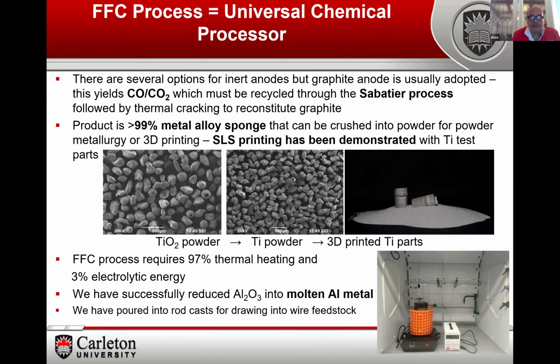This is an example of the technique applied to rutile. This is basically titanium oxide powder. This is the end result with the titanium powder after the process. And in addition, this potentially could be 3D printed directly in metal form.